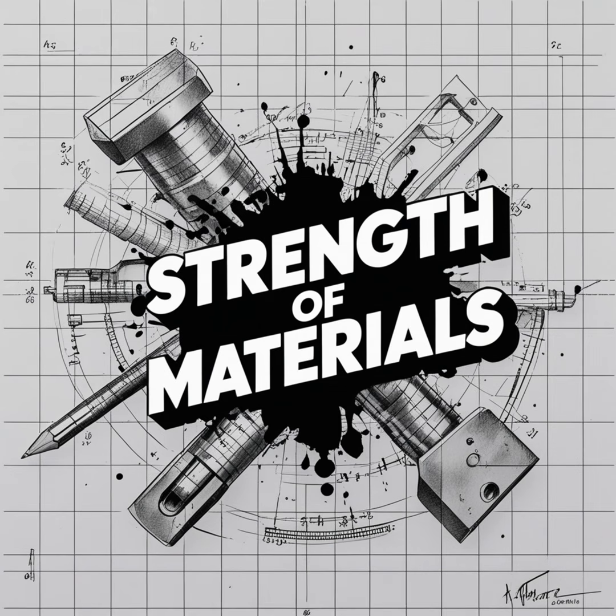I know from the literature it involves drawing a mathematical path, or a contour loop, around the crack tip. Exactly. The J integral is a path-independent line integral. Mathematically, you draw a line starting from the lower face of the crack, looping counterclockwise entirely around the chaotic plastic zone at the crack tip and ending on the upper face of the crack. In simple physical terms, what is this integral actually measuring inside that loop? Physically, it represents the rate of change of the net mechanical potential energy with respect to crack advance for a nonlinear elastic solid. But to put it much more simply, it is a direct measure of the energy flowing into the crack tip from the surrounding material.